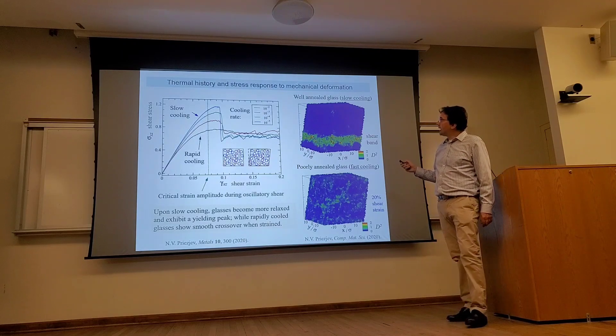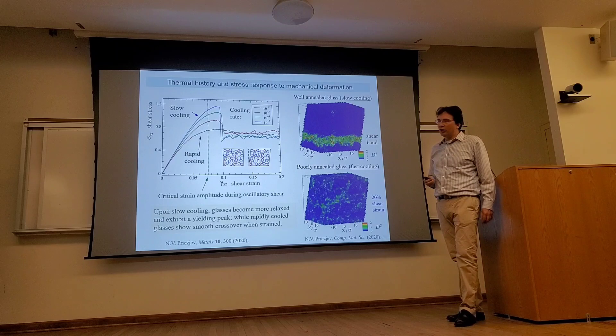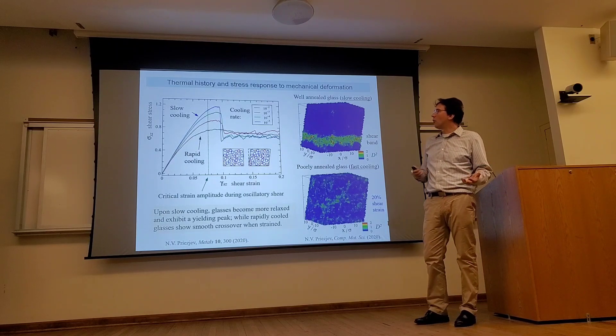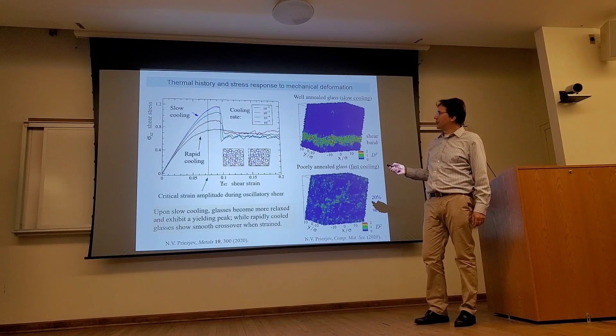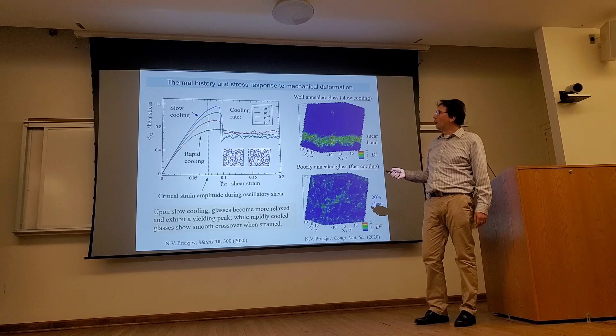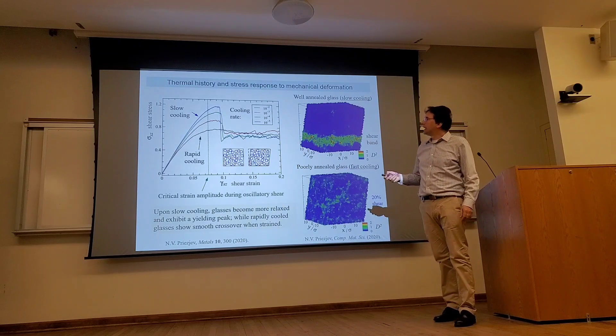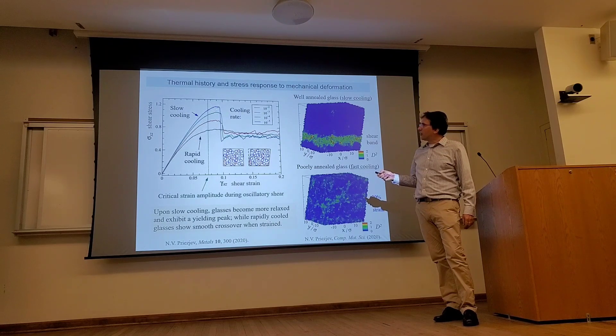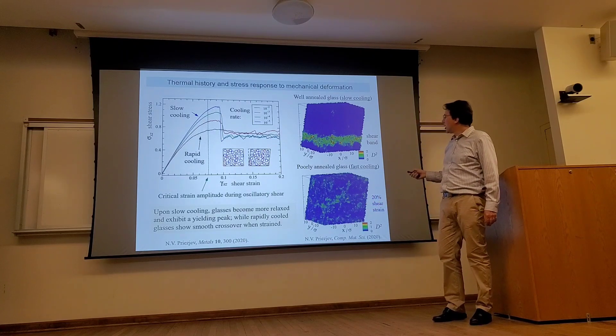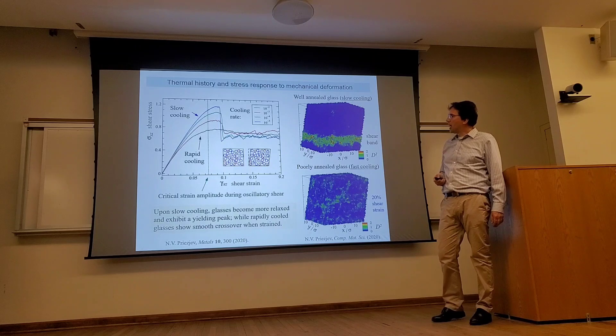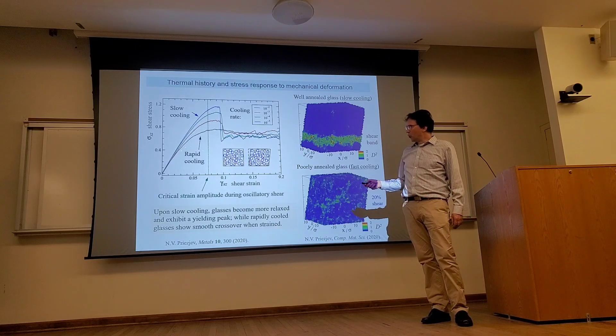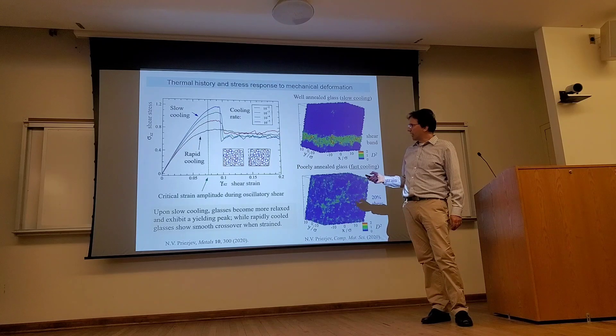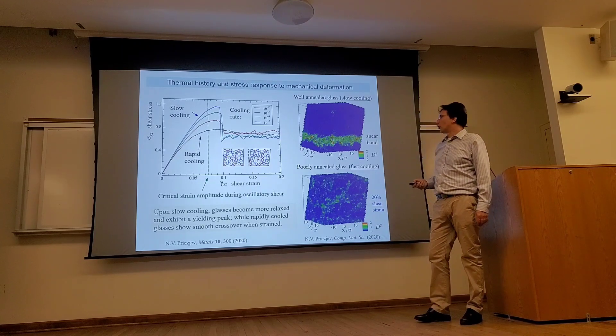What's also interesting is that the mechanical response of such materials strongly depends on the thermal preparation history. For example, if a glass is slowly cooled and then deformed uniformly, the mechanical response would consist of a pronounced yielding peak followed by a yielding transition via formation of a shear band. On the other hand, upon rapid cooling and straining, the shear stress exhibits just a gradual crossover.